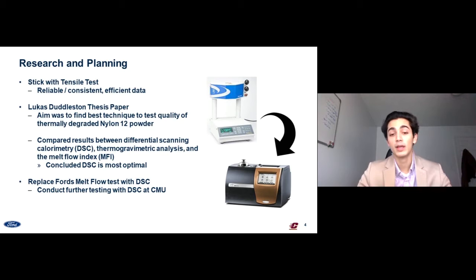Before we tell Ford to replace the melt flow test with the DSC, let's conduct some DSC testing on our campus because we already have that machine here. We'll get some powder from Ford, run some tests on campus, and prove to Ford that this test is much more efficient. Unlike the melt flow index, it doesn't take 45 minutes to test and clean the machine. It's very clean and repeatable, and we'll present that to Ford once we can conduct that testing at CMU.